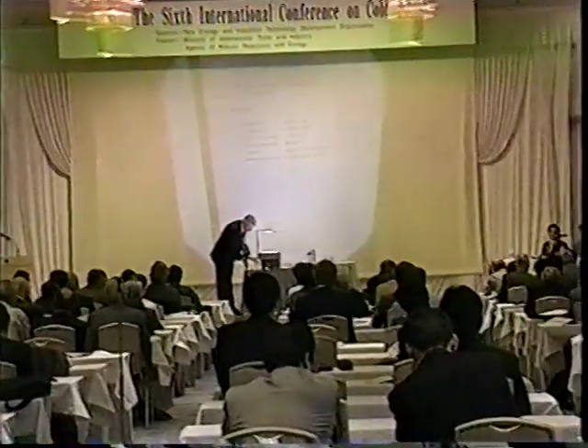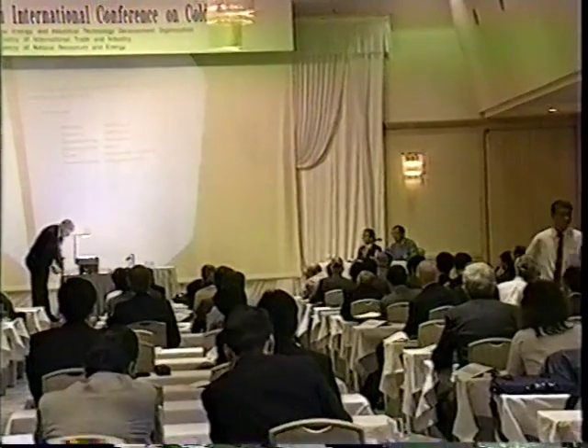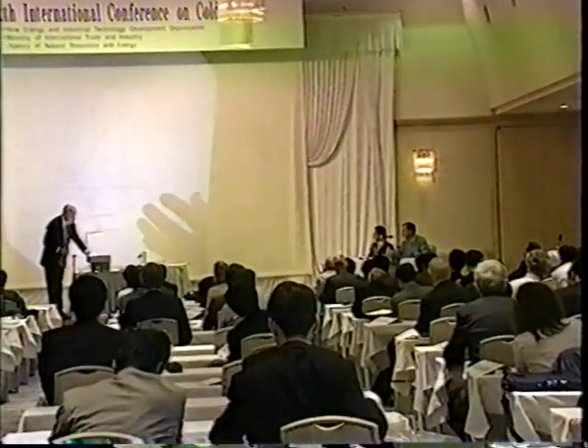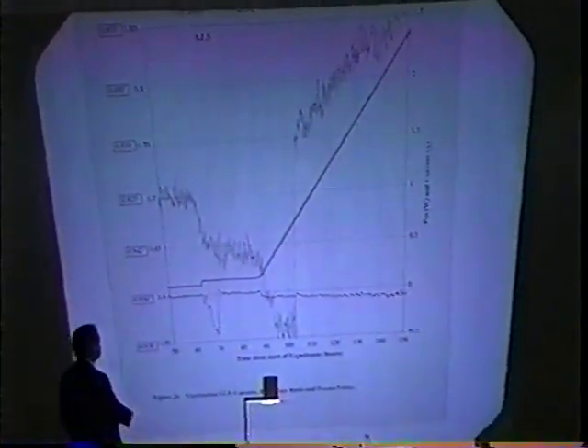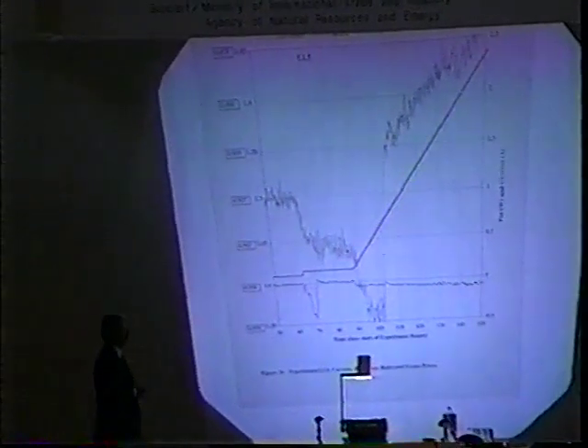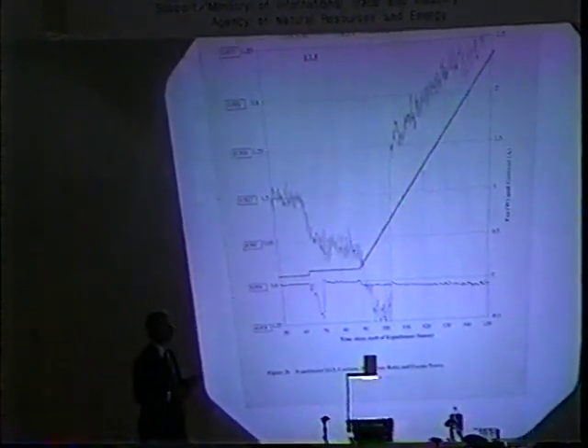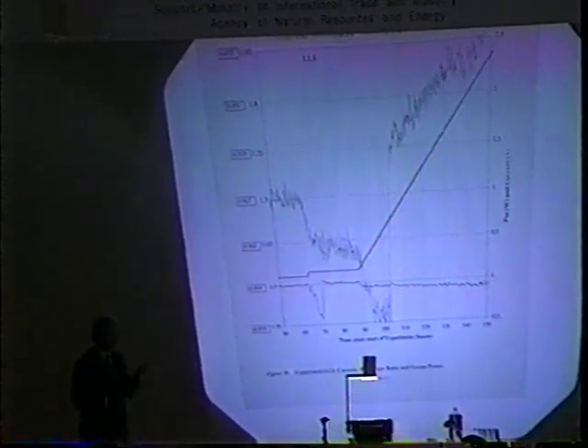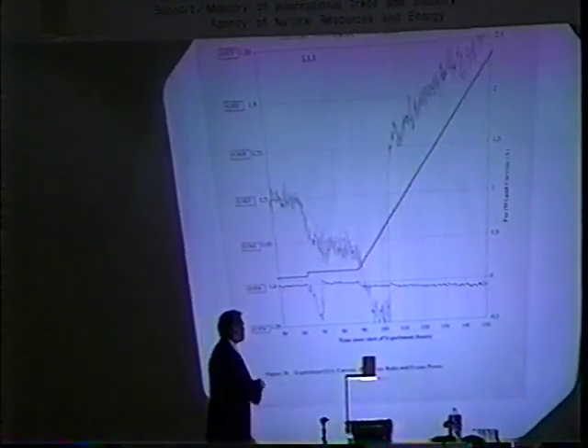You show that your energy balance is negative for a very long time. So where do you think this energy is going? You're talking about the non-steady state contribution on this curve? More than 100,000. Is that it? Yeah, and what's happening is that we're not doing this experiment under constant power control. The heater is turned off, so as the current increases and the power going into the calorimeter increases, the temperature of the cell contents increases. Because the temperature is increasing, we have to provide the energy which satisfies the heat capacity of the cell. So this is simply the non-steady state correction.